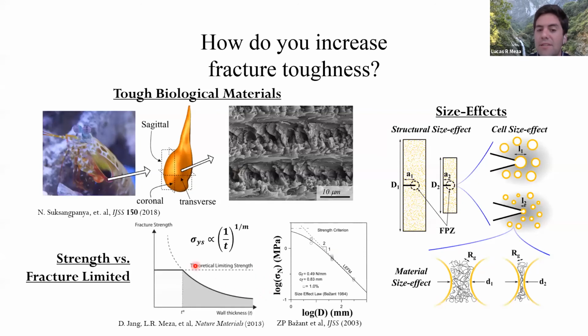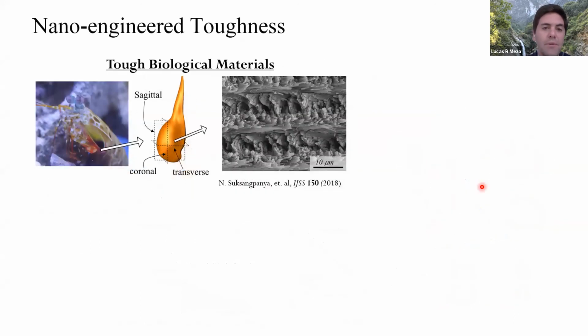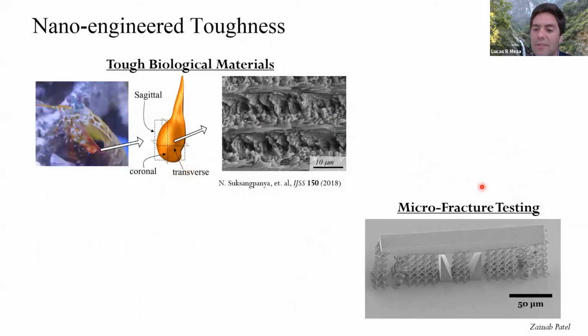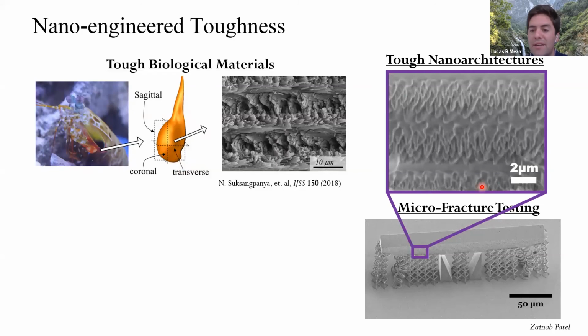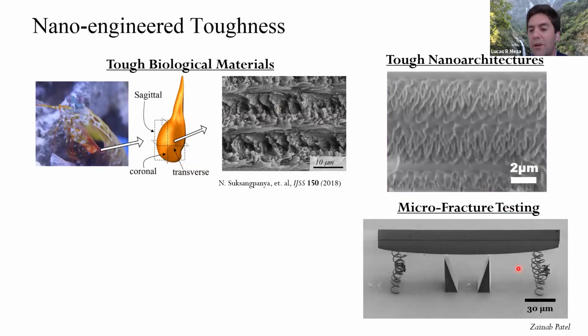So using this idea of statistical increases in strength, statistical changes in fracture mechanics to change the toughness of a material, from those tough biological materials, Zainab has been designing these micro fracture tests. You can see we can create these woven bouligand structures that qualitatively mimic that of biological materials. We can create micro 3-point bend specimens.